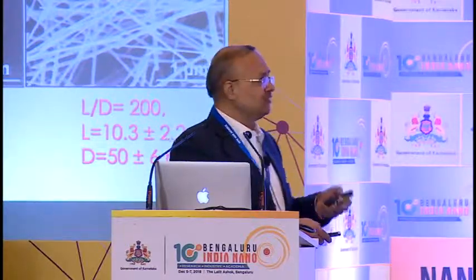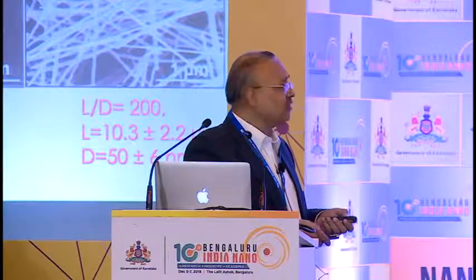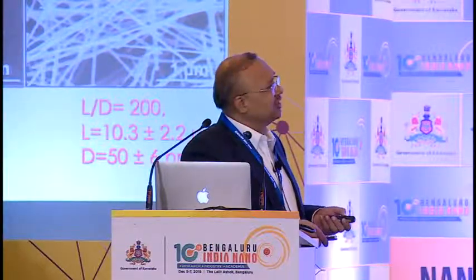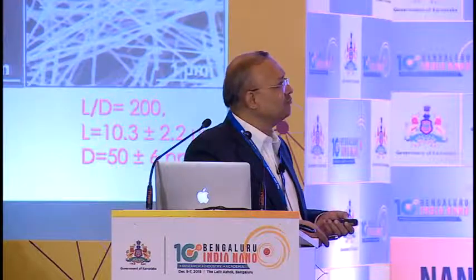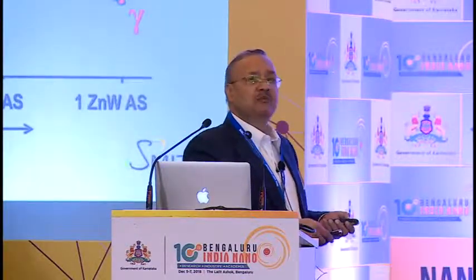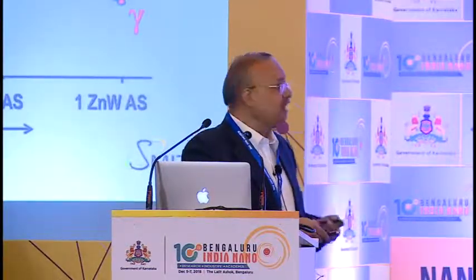So we are thinking of doing all these things which you do on semiconductors, on silicon and glasses and things like that. We're trying to create not textile as a substrate, but textile as a material. So there's a difference. We created one example. We created some nanomaterials. We synthesize everything from scratch, whether it is available from literature or not, because we need to have them in the right manner, in the right quantity, as well as the right dimensions. So we created particles, rods, wires of ZnO, and we added them into the fibers, inside a textile fiber.